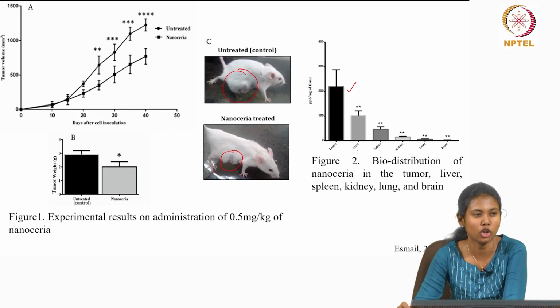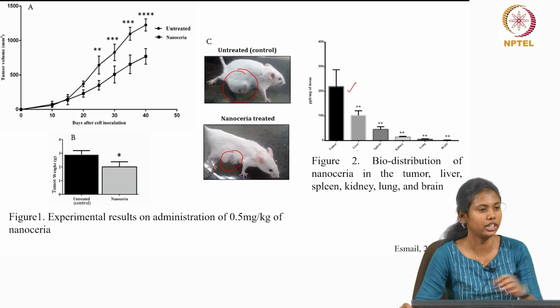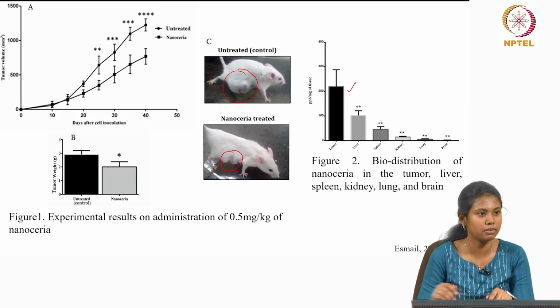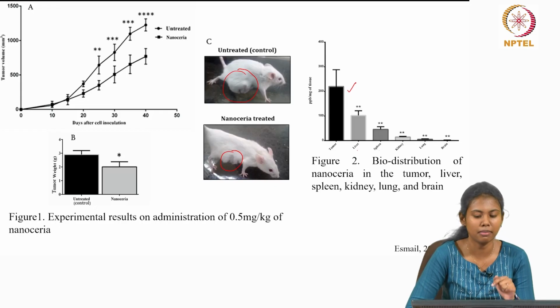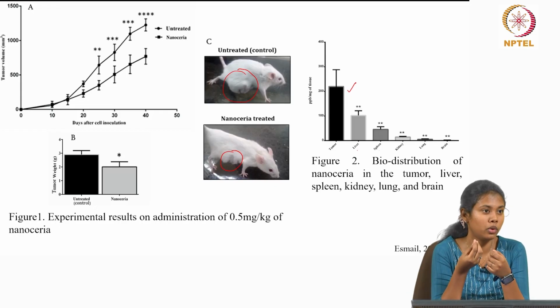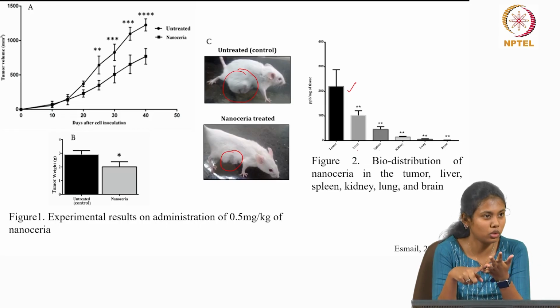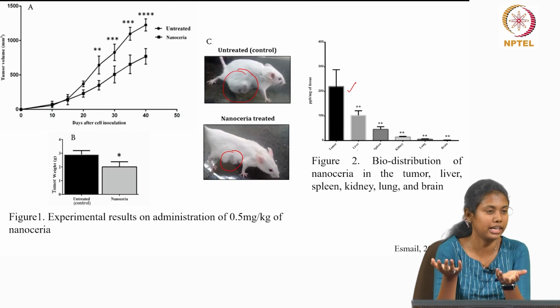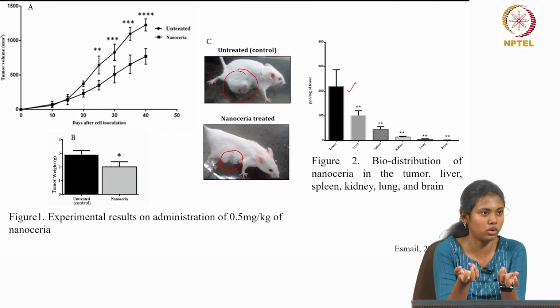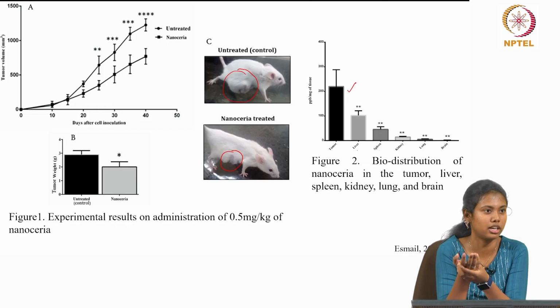I can't say there is no toxicity at all. But from studies, it is estimated there is no clear effect. The cytotoxicity of this was assayed, and in this particular study, they administered it to mice. They tested the metabolism, including the creatinine level, glucose, and certain other levels. When compared between normal mice and nanoceria-treated mice, it did not show any significant difference. All the levels of the biomolecules were similar. So from that, we can estimate there are no harsh side effects. There may be side effects, which is not precise.